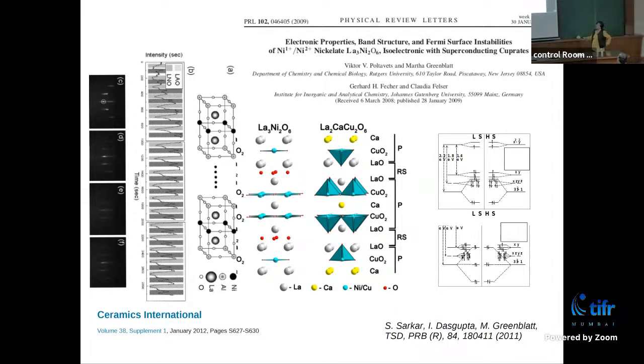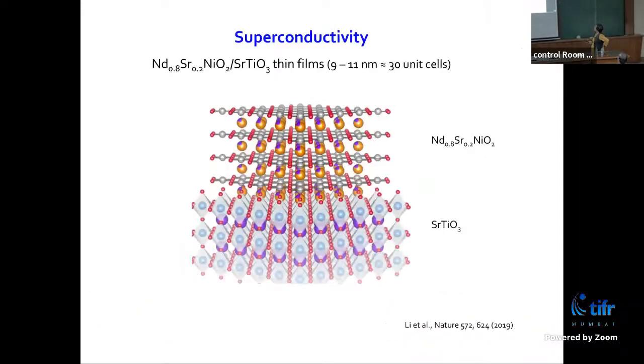She made bilayer, trilayer cuprate. She made a multi-layer nickelate and managed to get a combination of nickel 1 plus and nickel 2 plus, but not purely nickel 1 plus. She tried to dope it, couldn't find anything. So the matter ended there. Until in 2019, there was a big hype from the group of Harold Hwang from Stanford, who reported superconductivity in 20% strontium doped neodymium nickel O2 thin film put on strontium titanate.